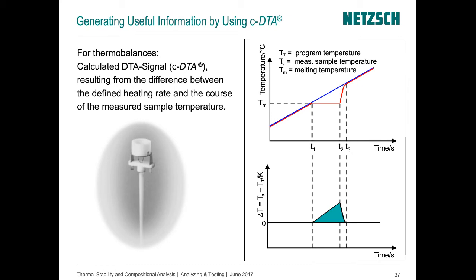Okay, thanks. I think we only have time for maybe two more questions. Can you comment on relative advantages and disadvantages of using alumina versus platinum TGA pans? Alumina versus platinum, did I understand it right? Yes, correct. So it always depends a little bit on the sample properties. A common aspect is that samples should not react with the crucibles they are put inside. For example, if you have some material which will melt during heating, then perhaps it can react with the crucible, and this should be avoided.